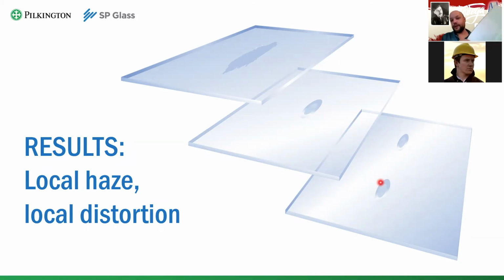It remembers, and on the facade, you will see this type of distortion. So it goes in the central part, and it is very sharp. This one is shown in the picture in the center. The same if you get 2 of them, even worse. So these are the signs of a bad tempering, improper tempering regime. And if you see this on the facade, you can go claiming.